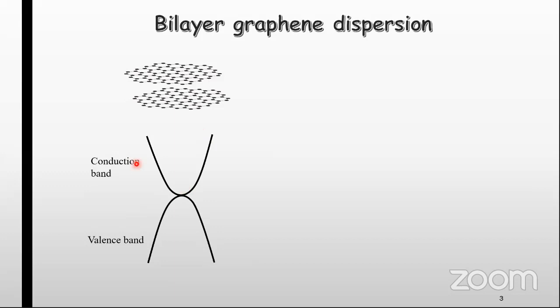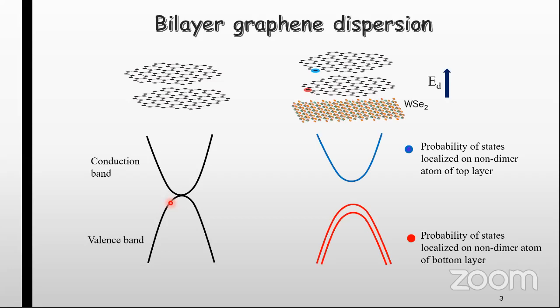So we understood that bilayer graphene has this low energy parabolic dispersion, and we know bilayer graphene is a weak spin orbit coupling material. If we put it on a single layer WSe2, which is a strong spin orbit coupling material, the band structure will get modified. For this heterostructure, there will be an electric field which will be out of plane, and therefore the two layers of this bilayer graphene will be at different potential. So the low energy band, which will be formed from the non-dimer orbital of the bottom layer, will be the valence band, and the higher energy band, which will be formed from the non-dimer orbital of the top layer, will be the conduction band. Now, since the bottom layer is in direct contact with the WSe2, it will feel a higher proximity, and there will be a large spin orbit coupling felt by that layer.